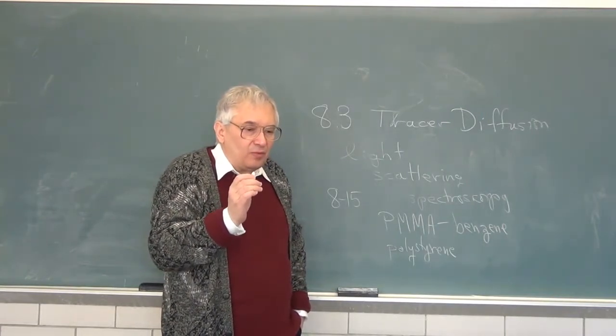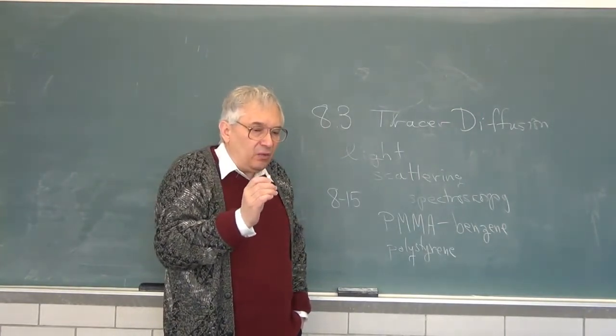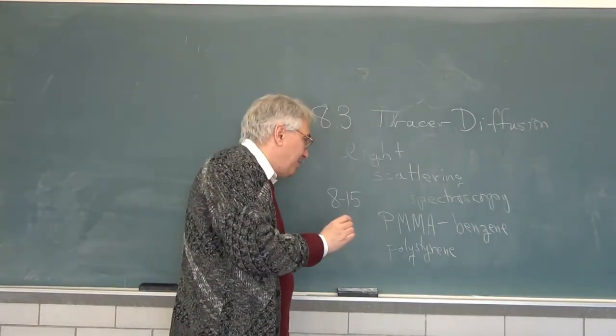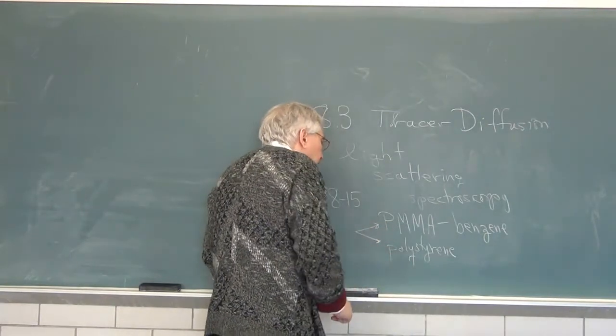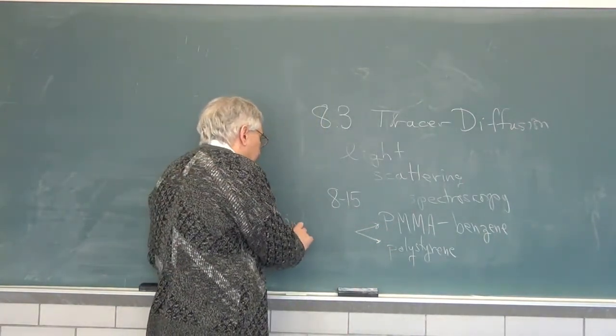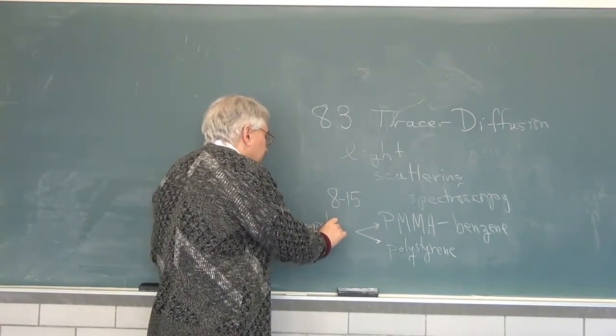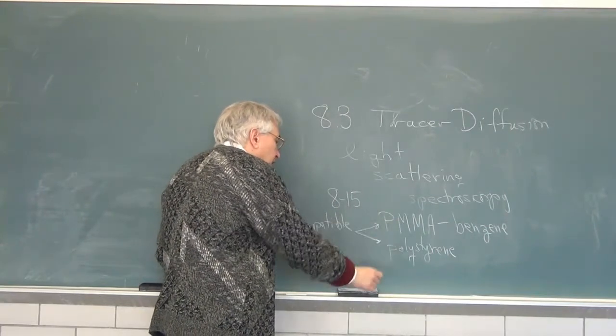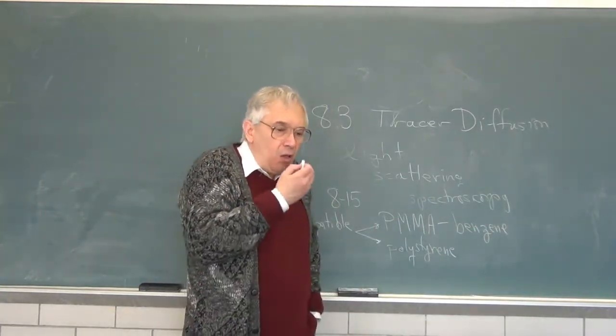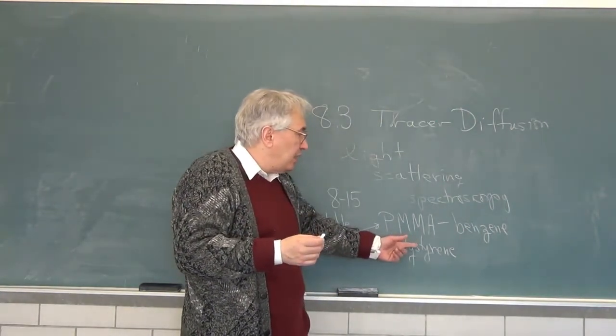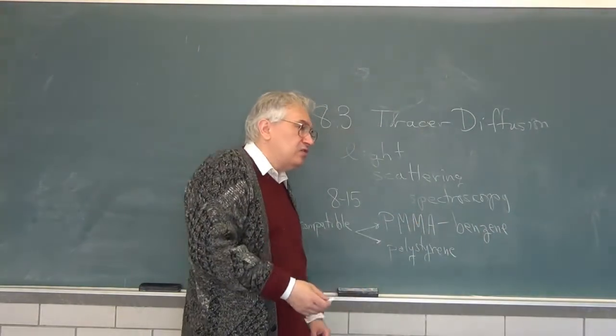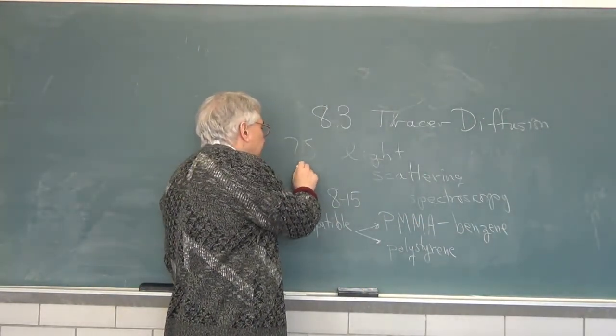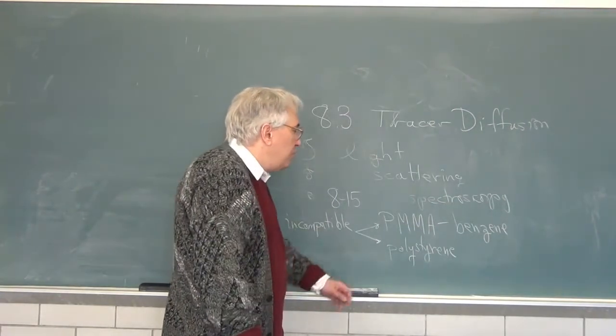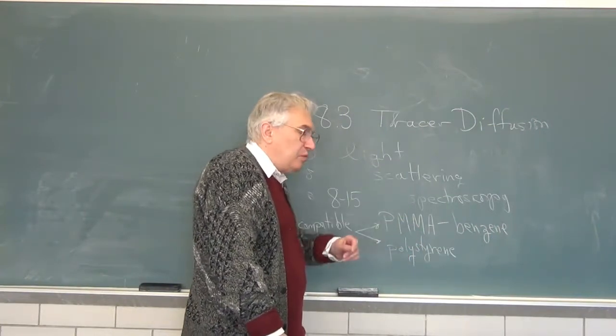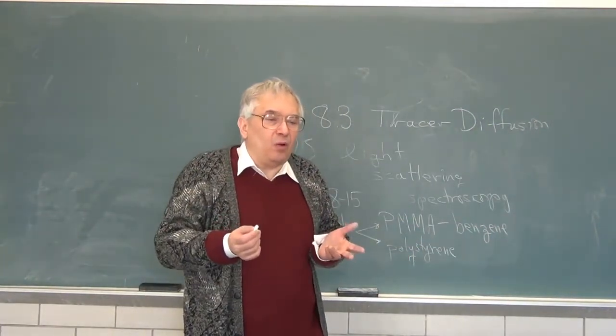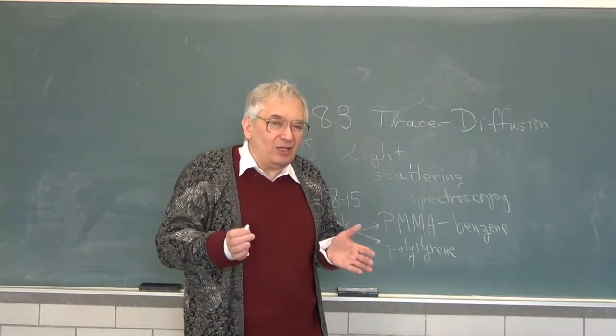Well, this works fine except for one minor technical detail, and the one minor technical detail is that these two polymers are incompatible with each other. That is, if you attempt to mix them, there's an unfavorable thermodynamic interaction, and the net result is that if you have a polystyrene chain and you add more and more PMMA to the solution, you expect the polystyrene chain will tend to get smaller and smaller because, on a molecular scale, it will be repelled by the PMMA. And therefore, you have a probe particle that is doing something inconvenient, namely it's shrinking.